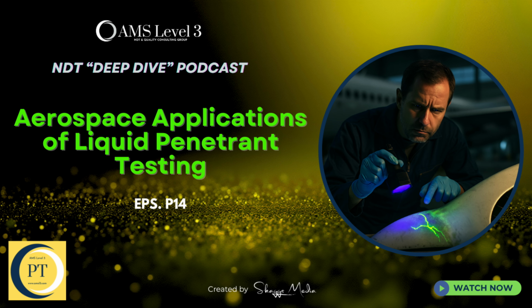This technique uses ultrasound at an optimized frequency to actively pump the fluorescent penetrant into the tightest discontinuities. It turns a passive soak into an active, energized filling process. And what are the benefits of using that ultrasonic energy? It provides three major advantages almost at the same time.